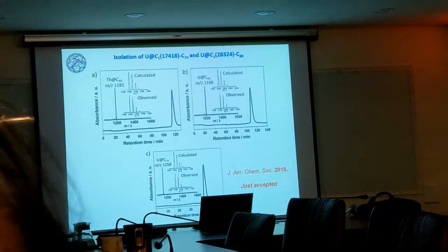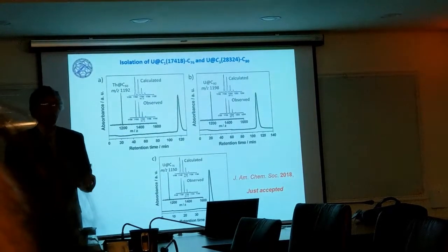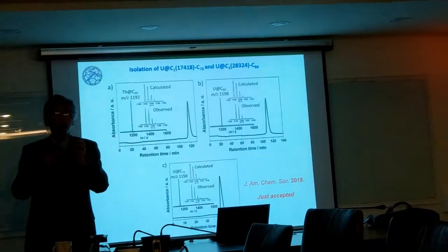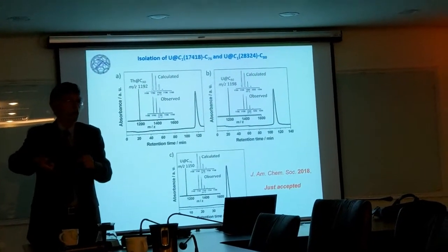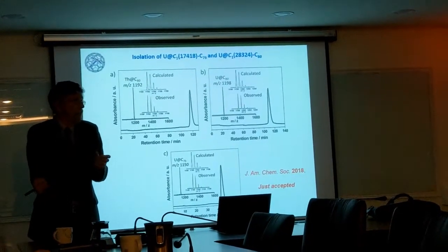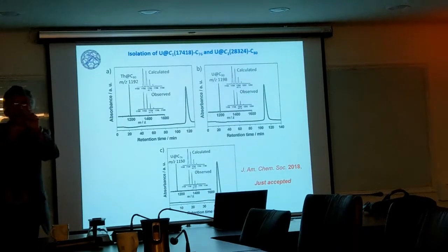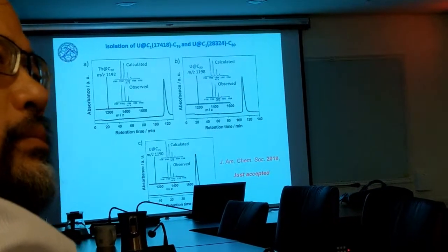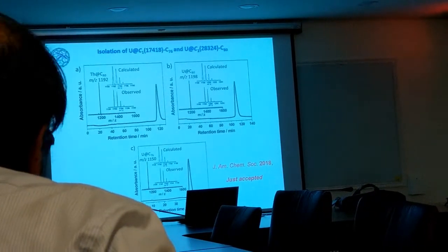If you don't have a recycling HPLC, you need to buy one, because it is actually not that much more expensive than a regular HPLC. You either turn on the recycling or not, so you can use it as a regular HPLC. And you can take something where you can barely see a shoulder, and you can separate it to baseline after 5 or 6 passes. It's really fantastic.